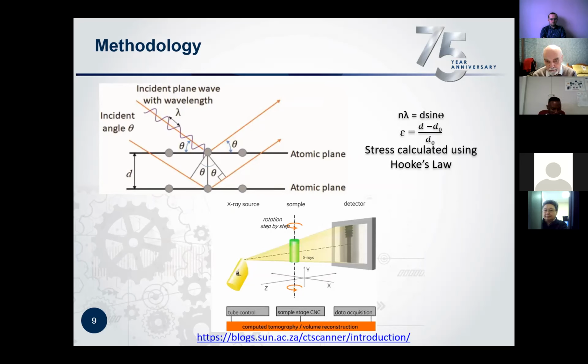Micro-CT, similarly, we just apply X-rays, but now these X-rays are not the same ones that we use for residual stress measurements. These ones are able to penetrate through the material. So you rotate the material, on the other side you have a detector that captures the images. And then later you can see through the material, see the pores in a 3D space. So these are the two techniques that we used in our studies.